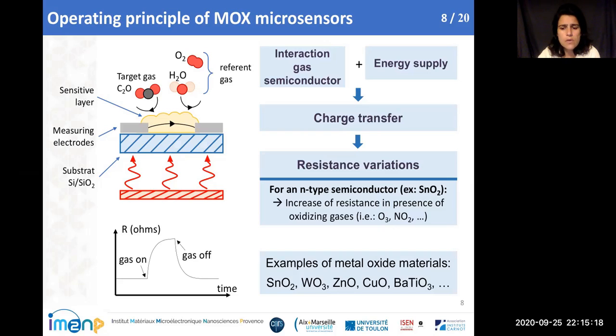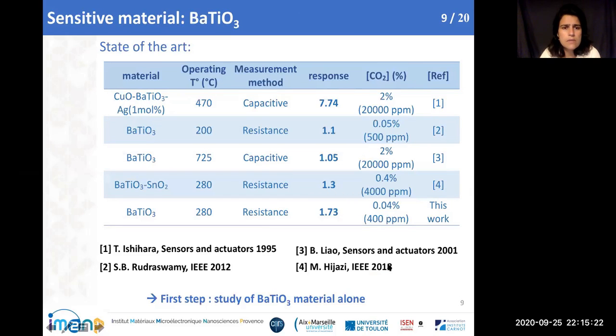So why have we chosen barium titanate? If we look at the literature, you can see that different works have been done with these materials, but sometimes with high operating temperature, or with capacitive methods, and with high concentration of carbon dioxide. In our case, we're going to try it around 280 degrees, with a resistive method and with 400 ppm.